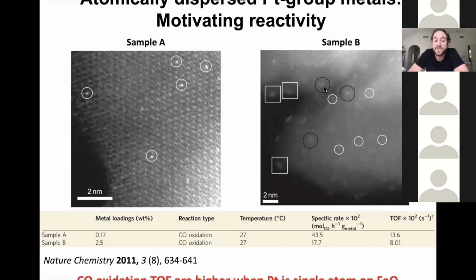If you went and measured the CO oxidation rate on these different catalysts, what you would find is the one that only had single atoms had a bit higher turnover frequency than the one that had clusters in it. And so from this, they inferred that these single atoms can have higher reactivity. So in the 3 examples we've seen, you have these dispersed species that can have a higher reactivity, can do complex chemistries, and can potentially have different selectivities than, say, small clusters of the same metal.